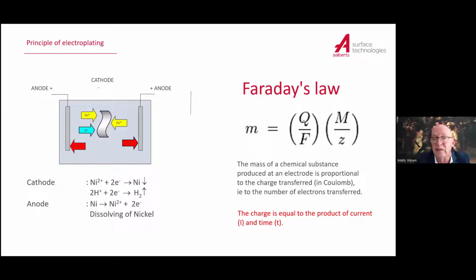you dissolve nickel. The complete process runs under Faraday's law, and that means that the mass of a chemical substance produced on an electrode is proportional to the charge transferred in coulombs, related to the number of electrons transferred. In simple words, you put on a current, and the height of the current and the time of your process will deliver the amount of nickel or metal produced.